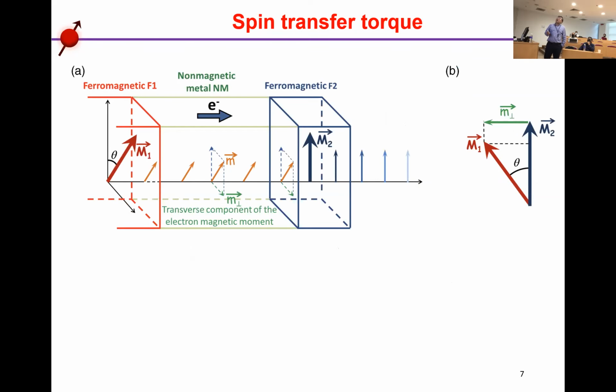So from here we can say, when an electric current passes through this ferromagnetic layer, suppose there is some angle between the two ferromagnetic layers. The angle is theta. When the charge current passes through the first ferromagnetic layer, it will generate a spin current, whose polarization is parallel to the magnetization of the first ferromagnetic layer. When this spin current passes through the second ferromagnetic layer, it will exert a torque on it, and then switch the magnetization of the second ferromagnetic layer.